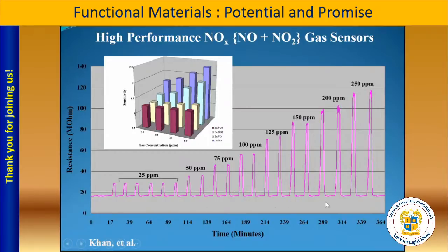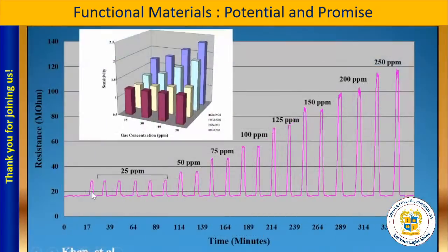Now you can see this is a room temperature measurement. You can see that in the presence of nitrogen oxide, the sensor response, the resistance increases. When you turn off nitrogen oxide, the sensor comes back. This is called response reversibility. This reversibility you can see from 25 ppm to 250 ppm. This is perfect, 100%. Now in the sensor world, this is almost unknown. If you get only 60 to 70% reversibility, you are lucky. But here you can see the quantitative result. This is almost perfect reversibility. The response time is less than a minute, with perfect reversibility.